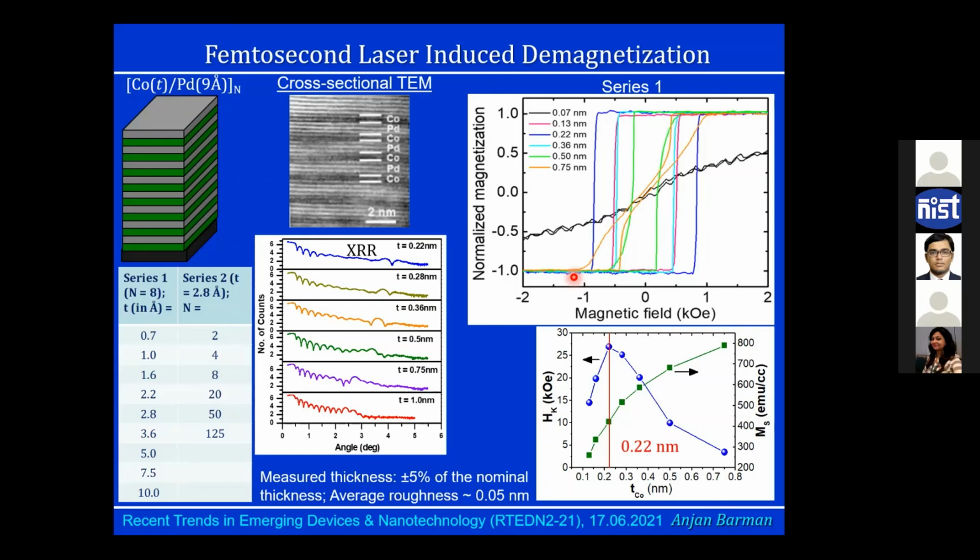If you go for modeling, which method would you emphasize, sir? Even for multi-domain thick films, you should model using finite element or finite difference method-based micromagnetic simulations, because it is a continuum model. If you cannot model this kind of structure using a discrete spin model like the Ising model, that will not work. Electronic structure calculations will also not work.